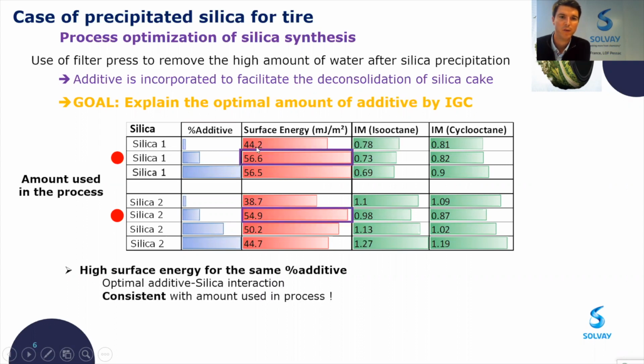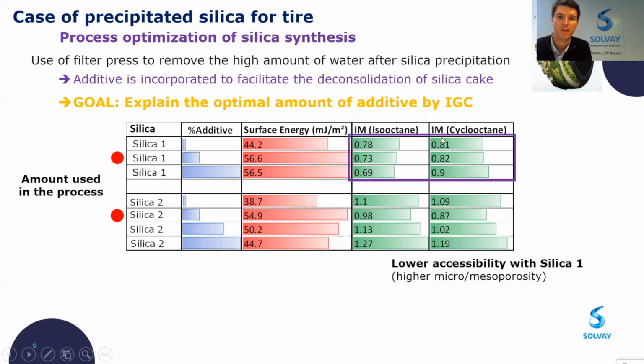And when we see the value of surface energy, we tend to decrease the surface energy when we increase the amount of additive. So we have an optimal interaction between the additive and the silica for this amount of additive. And when we increase this amount of additive, we tend to make some cluster of this additive and generate some heterogeneity at the surface. Concerning the morphology index, as you can see here, we have a decrease of the morphology index for the silica 1, and it is in good agreement also with the textural properties of the silica compared to the silica 2, exhibiting a higher micro and mesoporosity.